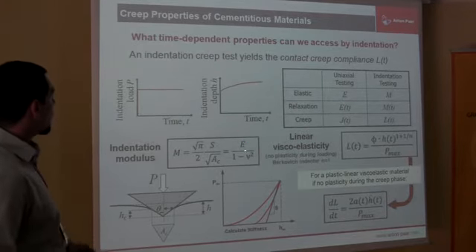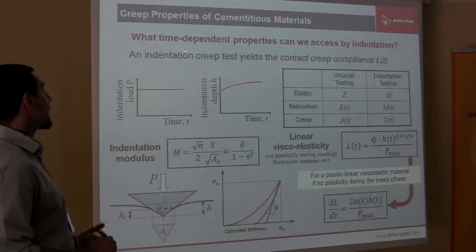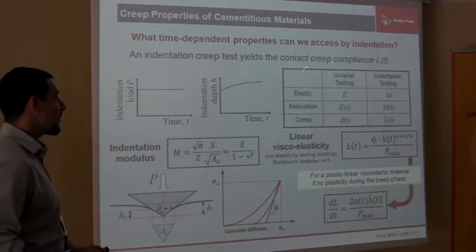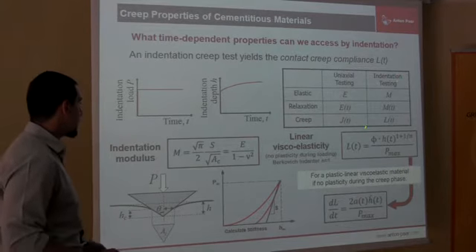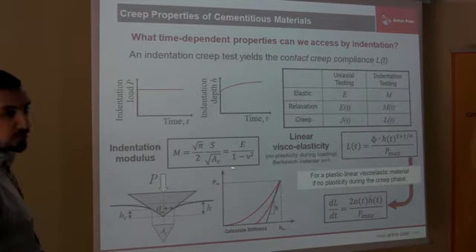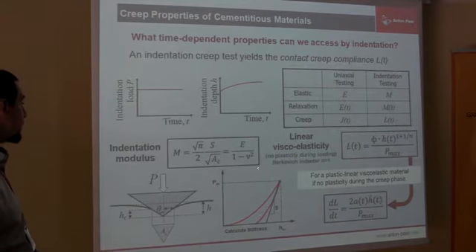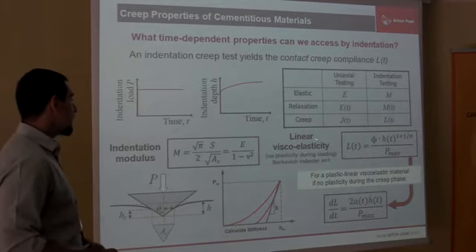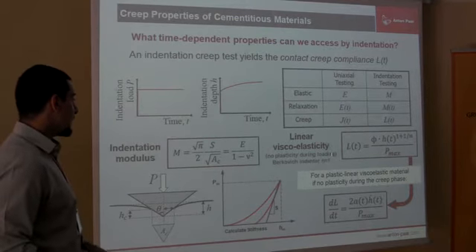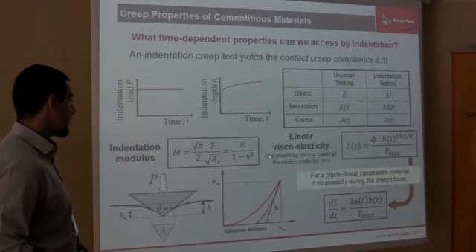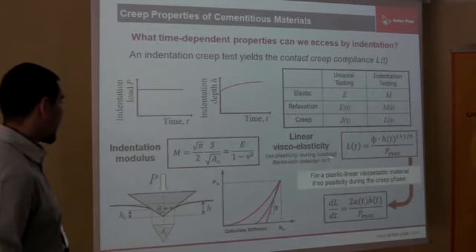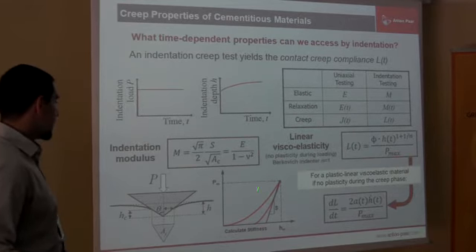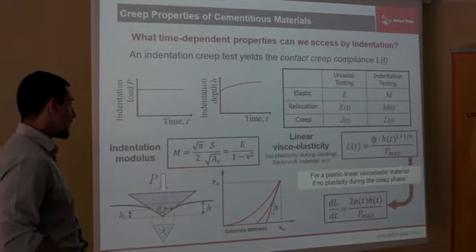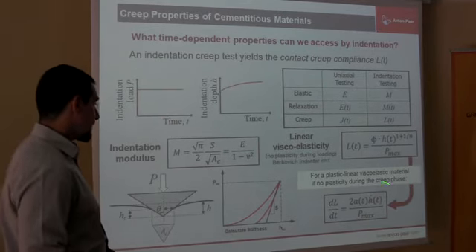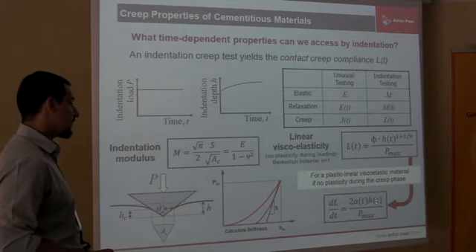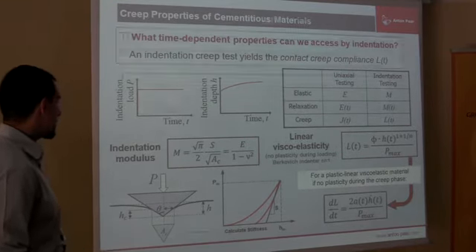But we have to think about what time-dependent properties we can see with the indentation test, and these are the indentation modulus, which is strictly connected with the elastic modulus and the property of the material, and the linear viscoelasticity. In this case, we have no plasticity during the applying of the load, and this is the evolution of the linear viscoelasticity with time, connected with the penetration inside the material.